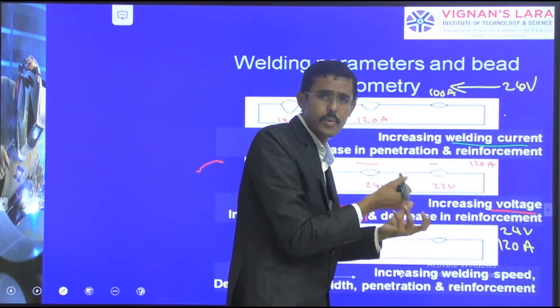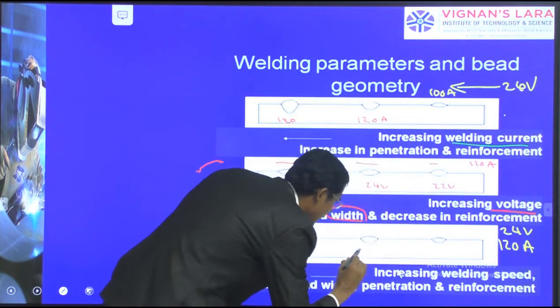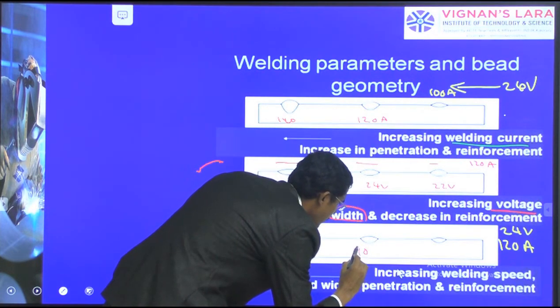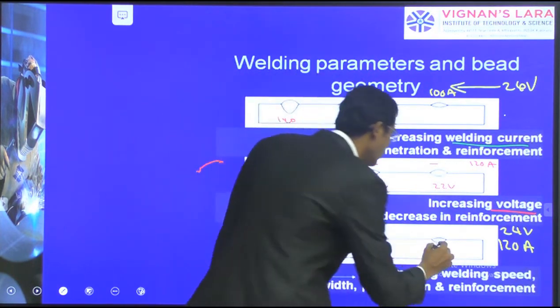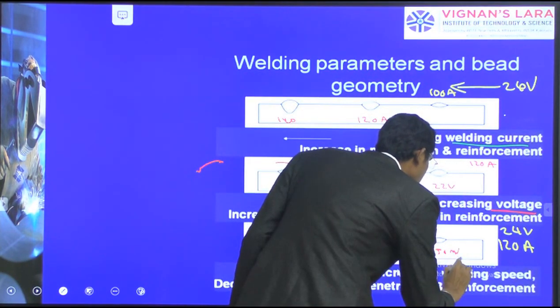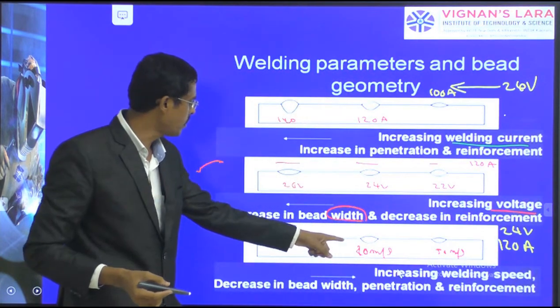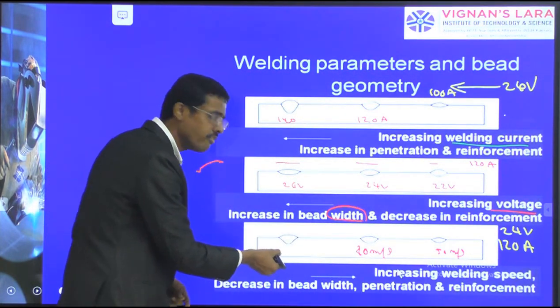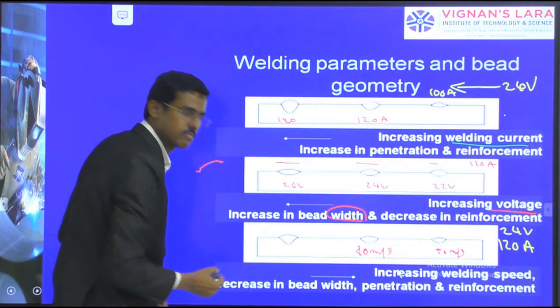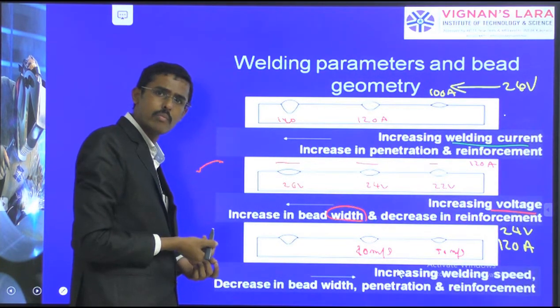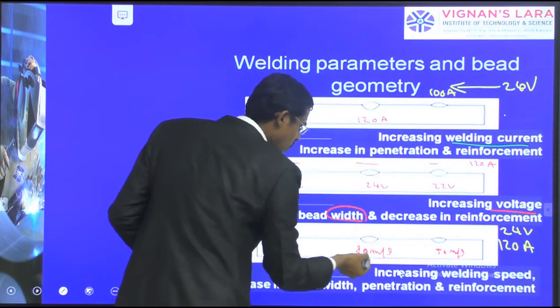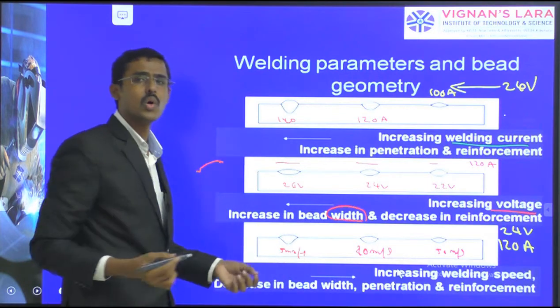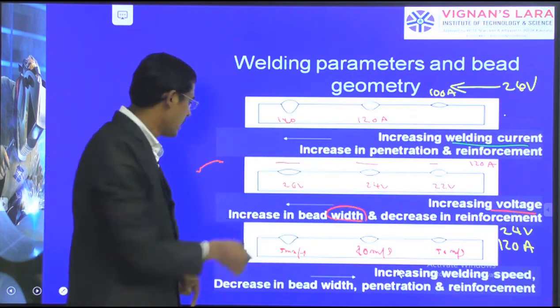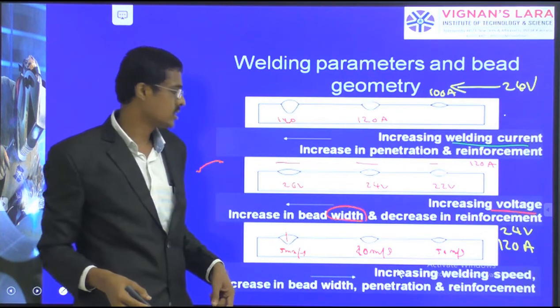The optimized welding speed to be given, let us consider, is 10 or 20 mm per second. But here we have done 50 mm per second. We are going very fast. This is the optimal level we have done. And if I go very slow, 5 mm per second, more heat is generated here and the penetration goes deeper.